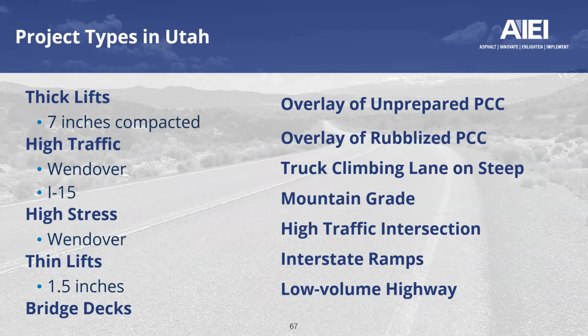Wendover is certainly a high stress location. We've seen it in thin lifts, including 1.5 inches on top of bridge decks. We have overlaid both rubblized and unprepared PCC on I-15 and 215 respectively. It has been used in truck climbing lanes on the interstate as well as U.S. highways in some of the steeper mountainous areas where they've really struggled to keep an asphalt mixture long term.